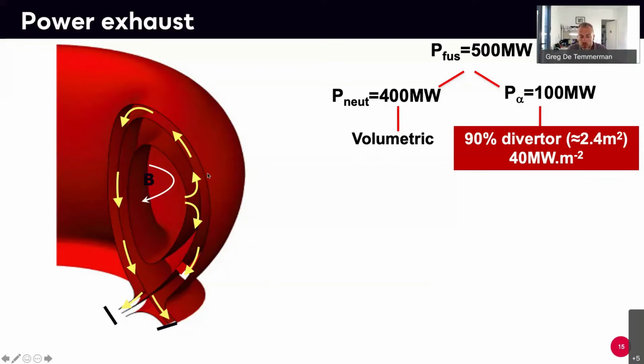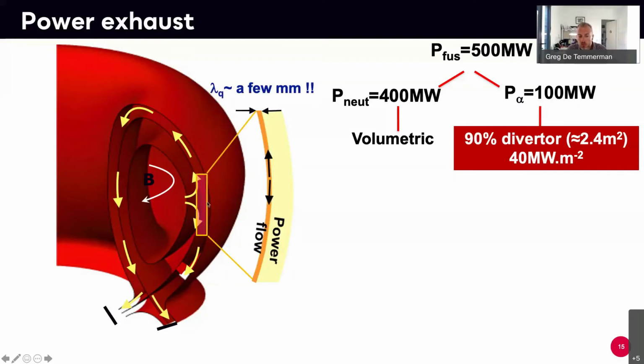And because of the magnetic geometry, the power is going to be deposited in a very narrow region, because when particles come out of the plasma, they move extremely fast along the magnetic field, but of course very slowly across the magnetic field, because the field is extremely strong in a tokamak. So when they follow the field lines and deposit their energy at the bottom of the machine, we only have a very small area inside the machine where the power is deposited. So if you take ITER, you have about 700 square meters of surface inside, but the power is only deposited on about 2.4 square meters. So if you do the math, I have about 40 megawatts per square meter to exhaust in this area, which is a lot for a material. And actually no component or no material can actually take that.